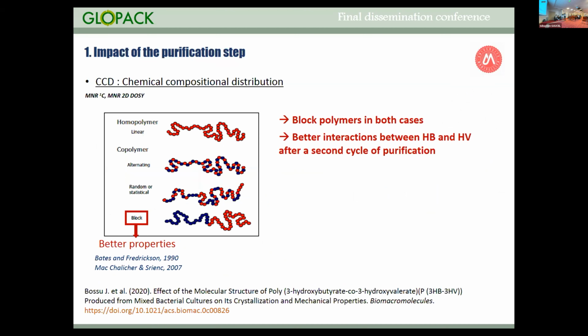Here in literature, it is well described that if you have some copolymers, you can have different types of 3D organization, either alternating polymers, so it's a regular alternating of the two kinds of monomers. You can have random polymer, or you can have block copolymer. And it is largely demonstrated that if you have block copolymer, so with block of HB, then block of HV, and block of HB, block of HV, you have better interaction between these blocks, and so better mechanical properties.